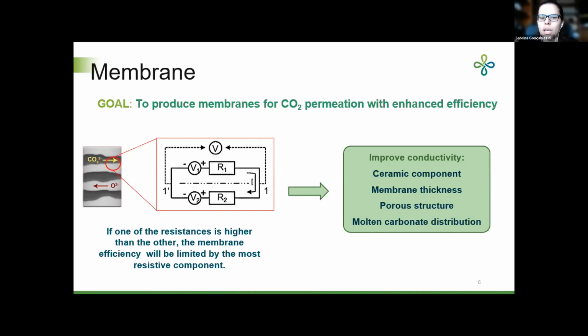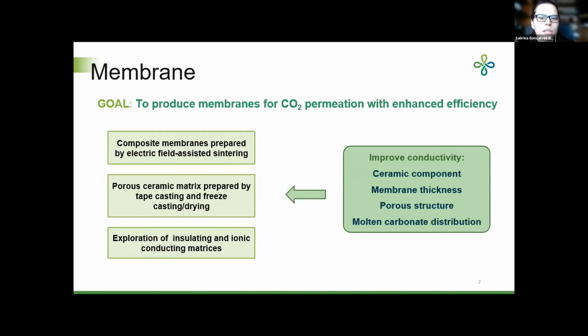With that in mind, we can think of different strategies to improve the conductivity, such as changing the ceramic materials to be used, or somehow improving the conductivity of these materials, decreasing the thickness of the membrane, and maybe changing the pore structure in order to decrease the tortuosity, and also studying the molten carbonate conductivity and distribution inside the membrane. So considering these parameters to improve the conductivity and the permeation, we came up with some strategies in order to improve the final membrane.